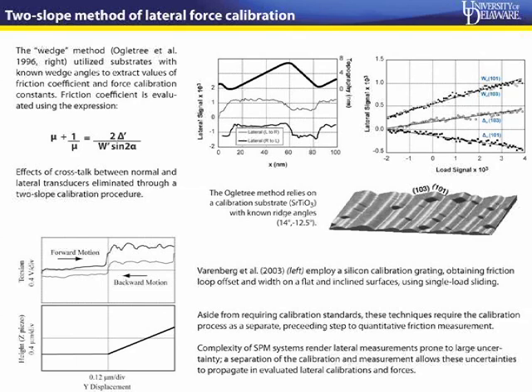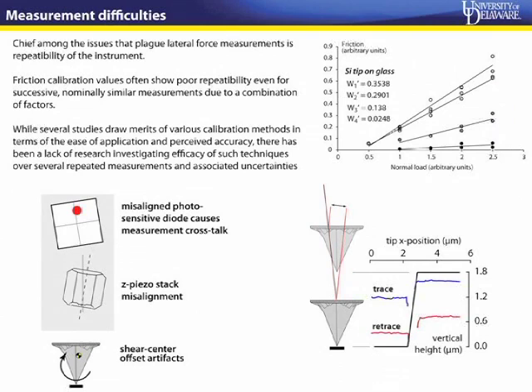However, the problem with most of these methods is the complexity of the AFM or SPM system. Because of that, these calibration methods are prone to large uncertainties, and it dilutes the confidence that you have in the quantitative friction measurements at the nanoscale interface. And one of those difficulties is merely the misalignments that you might end up with in an instrument. As Ogletree and several other authors also point out, you might have misalignments of the photodiode, which is really the detector of the laser reflection in an AFM, with respect to your translation axis. You might also have z-piezo stack misalignment and shear-center offset artifacts, which are going to essentially throw off the accuracy of your measurements.